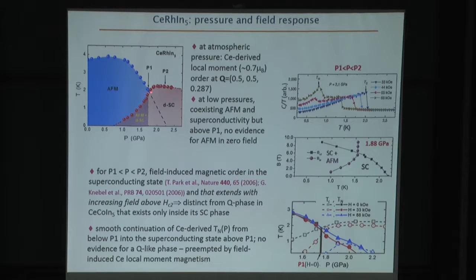But once the superconducting transition temperature becomes equal to the Néel temperature, at any higher pressures, there's no evidence in any experiments for this magnetism. It suddenly disappears, and at pressures above P1, there is only superconductivity, at least in zero applied field.